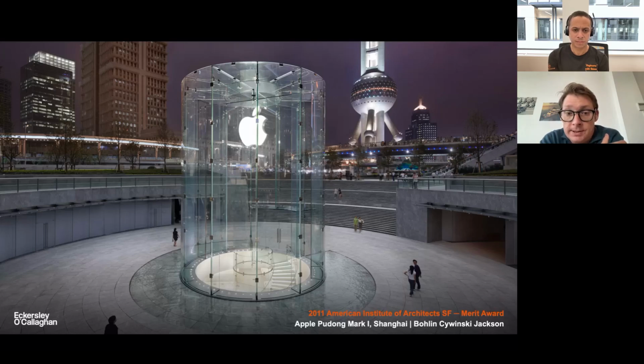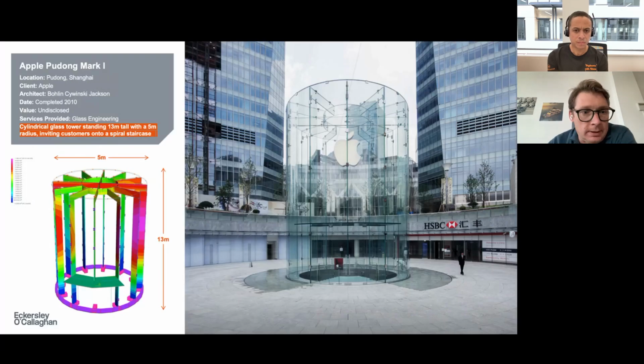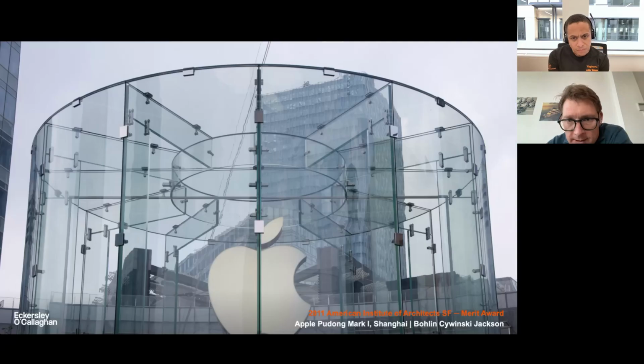And so this is made of 2 sheets of 15 millimeter glass in the facade panels, and the internal structure supports all the vertical weights coming down to the plaza level. And the little diagram on the right shows you that in a bit more detail. So we can see we've also got a curved central ring, which is bringing together all those beams, and so we have this open central oculus at the largest panel we could.